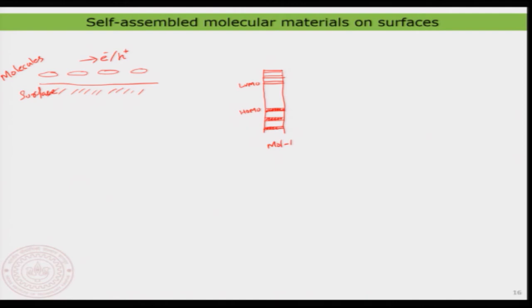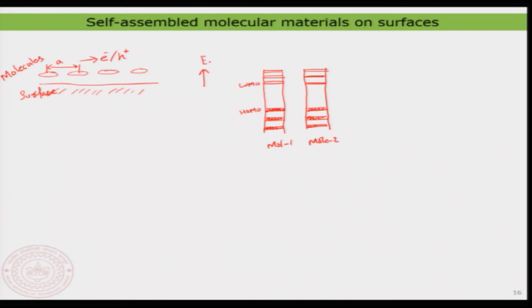When you arrange molecules together, there is a spacing A between them given by the geometry of the molecule. The next molecule — molecule 2 — has the same filled and unfilled molecular orbitals. This continues in all directions. The energy gap for a typical semiconducting molecule is on the order of a few electron volts, or in some cases even smaller like half an electron volt — this is the EG, the energy gap between HOMO and LUMO.